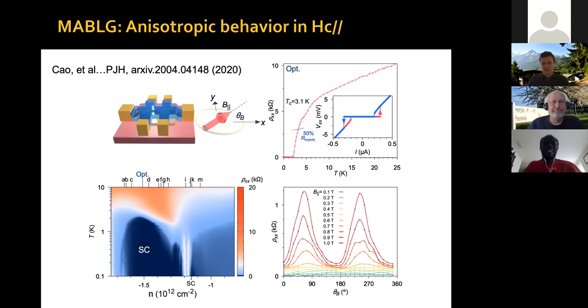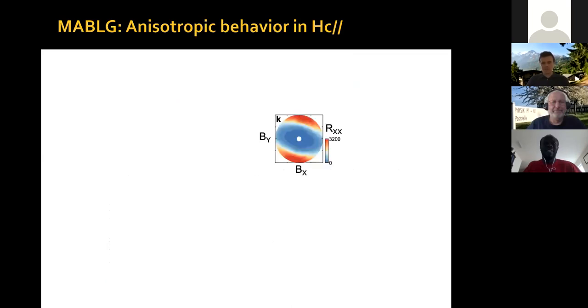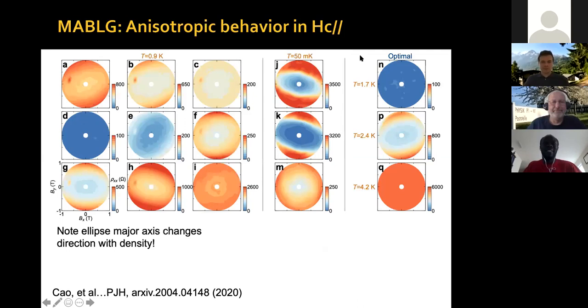So as I told you, the response of the system is an ellipse. And here you have the ellipse, okay? If you plot it in polar coordinates, Rxx versus Bx and By, what you can see is, this blue region means it's superconducting. So the system has a much higher in-plane critical field along this direction than in this direction, okay? In this direction, the system goes from blue to red. So the critical field is below 1 Tesla. Here, it actually is larger than 1 Tesla. So it's blue all the way to the edge, okay? Now we can do this at different dopings, okay? And we can do this at different temperatures, etc.